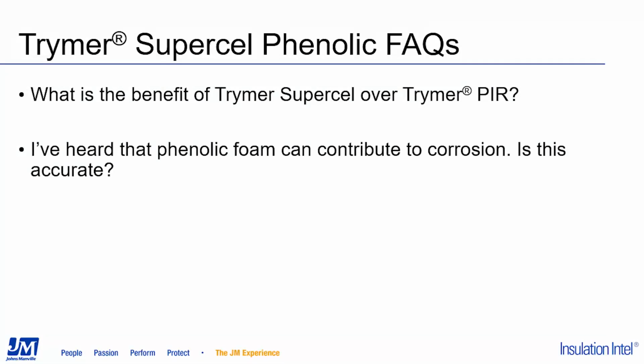This roof insulation was strongly linked to extensive problems with corrosion of the metal roof deck. Lots of lawsuits related to that are still making their way through courts. Compared to the problematic phenolic roof insulation, the phenolic pipe insulation,